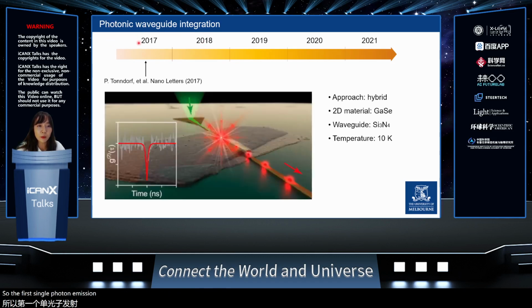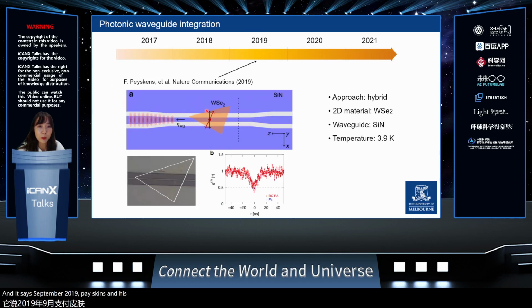The experimental demonstration of waveguide integration has a relatively short history. The first single photon emission from a layered material coupled to an on-chip waveguide was reported in 2017 by Tonndorf and Benson in Nano Letters. They reported single photon emitters in layered gallium selenide coupled to a silicon nitride photonic waveguide, and this experiment was conducted at 10 Kelvin. In September 2019, Peyskens and his team reported the integration of a WSe2 monolayer onto a silicon nitride chip, and single photon emission was validated. In this case, again, the measurement was conducted at cryogenic temperature.